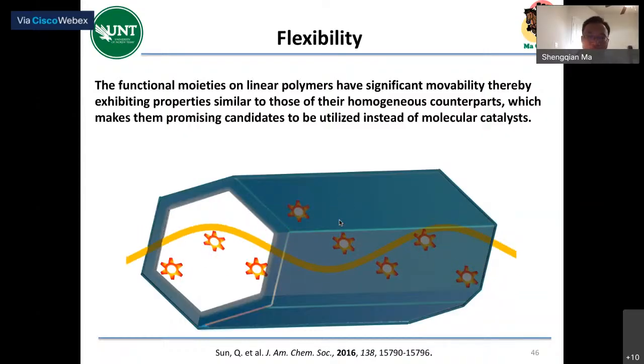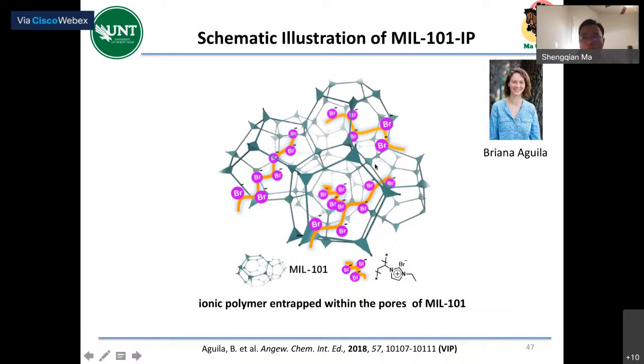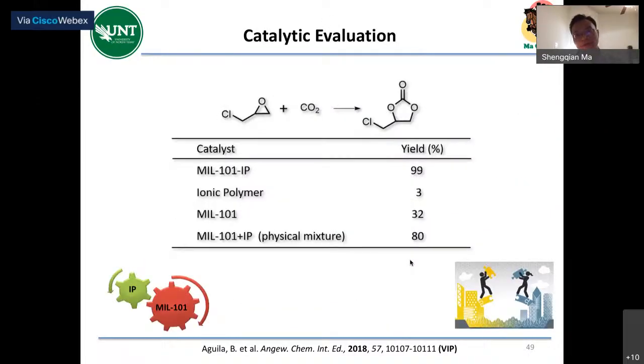Flexibility. So bearing this in mind, we pick this MIL-101. It has the open metal site because the cyclic carbonate formation is Lewis acid catalysis. Use some hydrogen bond donor, that's the co-catalyst. We can thread in this polyionic liquid, right? With the bromide as a co-catalyst. So this is the basic composition. So we pick this reaction, cyclization of this epoxide. And then we thread in the ionic polymer. We can achieve very high yield. It's much better than the MOF, also better than the physical mixture, because MIL-101 itself can catalyze a little bit, and it's better than the physical mixture.